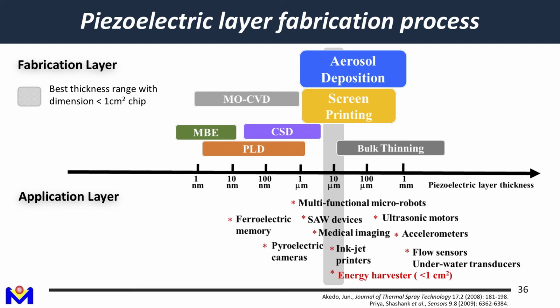And the other major method, as you can see in a lot of research, is thinning from a bulk PZT material. For bulk PZT material, the sintering processes are like sintering a ceramic plate or ceramic cup. It has a thickness limitation. It's very difficult, hardly possible to go below 100 micron. The reason is very simple. When it's too thin, it becomes too brittle in the sintering process.